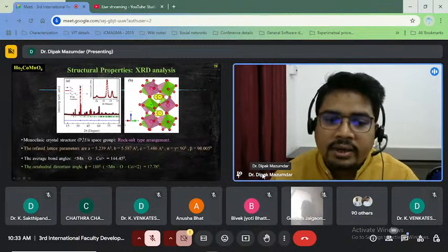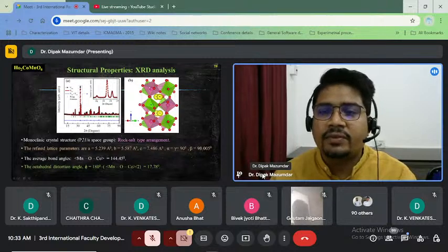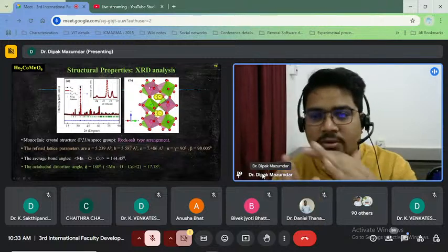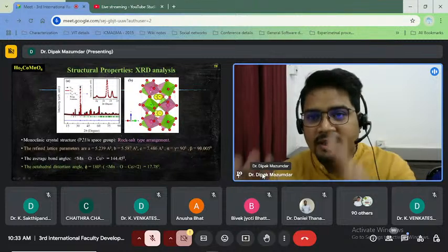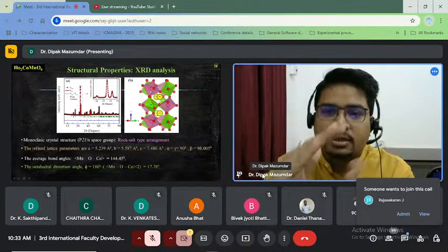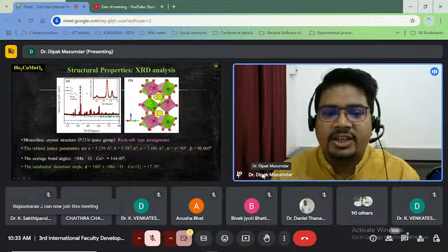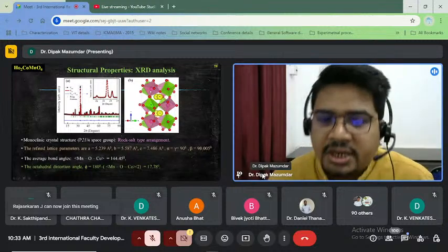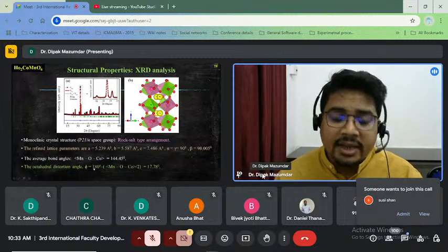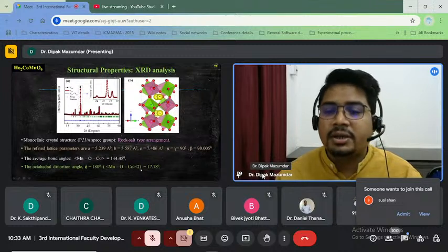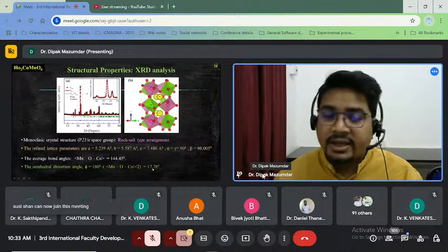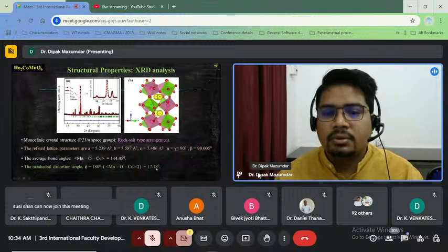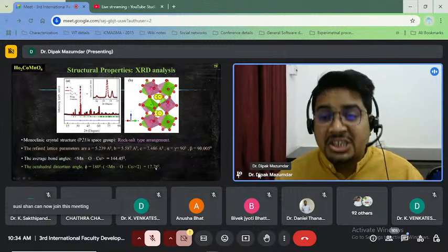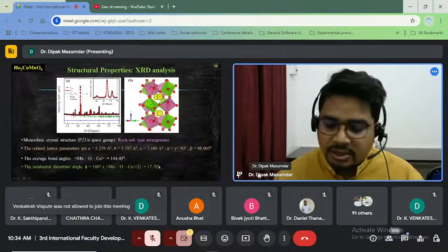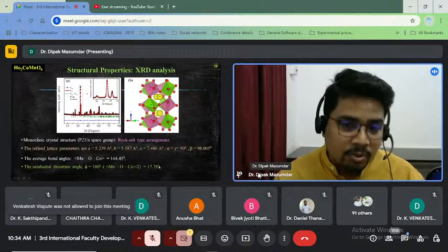And the octahedral distortion angle: you can see this is not a perfect octahedron, this is something tilted. The cobalt is tilted like this and manganese is tilted like this. So what is this average tilt angle, or the distortion angle? That can be calculated by using this formula, and it comes to around 17 degrees. So it's too high. In the ideal case it should be 0, but it is 17.78 degrees. So this will give some fascinating properties.